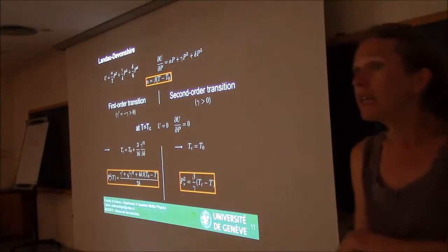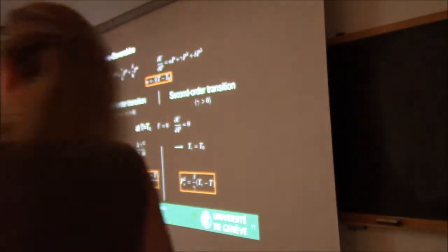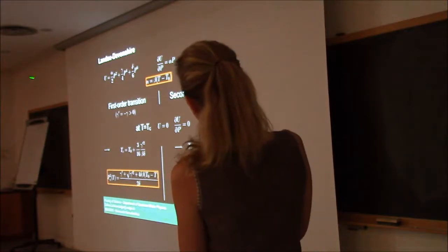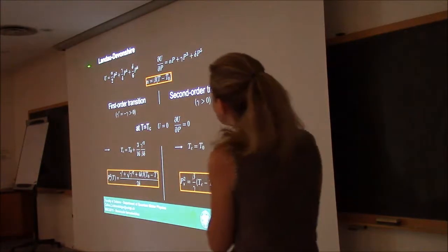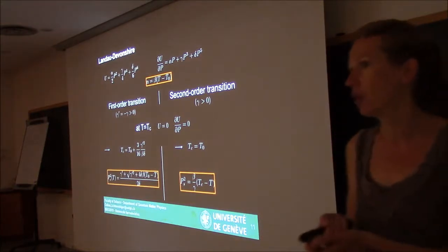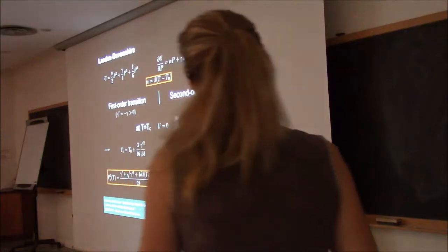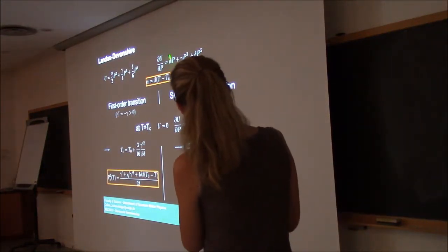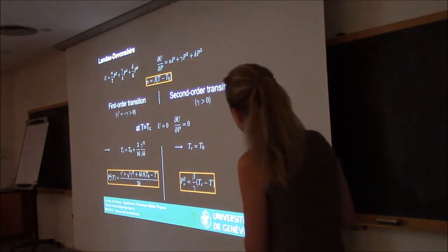It can also be expressed following the Landau-Devonshire approach. So here, again, I'm expressing this energy, but this time directly as a function of the polarization, which is used as the order parameter. And so when you do the calculation, you look at the derivative of the energy, and you express this alpha as a function of the temperature.